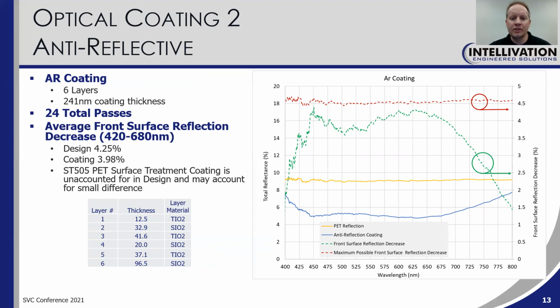The chart over here shows a number of things. The yellow curve is the reflectance of the bare PET. And so we're seeing the reflectance on both the first and the second surface. And the blue curve is the performance after coating. And then the red and the green describe the theoretical maximum performance compared to the actual performance.